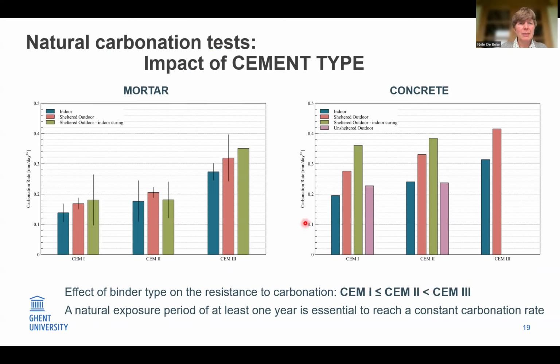We also tested under natural carbonation conditions, and then we did obtain more or less the same order for carbonation of the different cement types, both for indoor and sheltered outdoor conditions, and both for mortar and for concrete. And when we looked at calculation of carbonation rates, it seemed essential for natural conditions that the exposure period was at least 1 year to reach a constant carbonation rate.